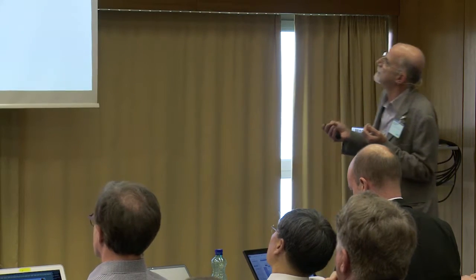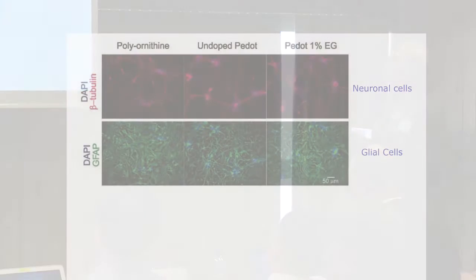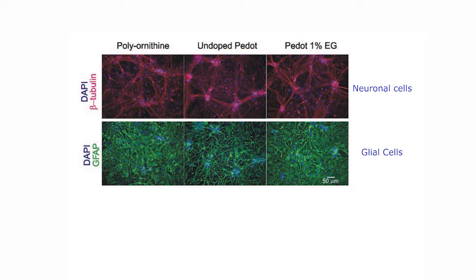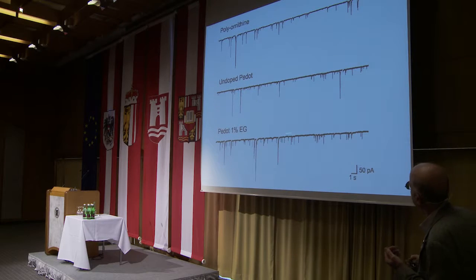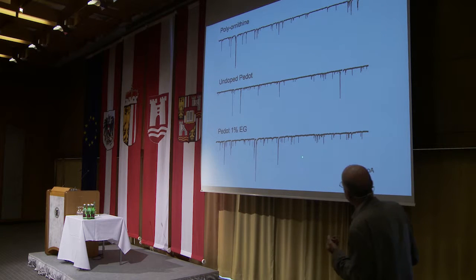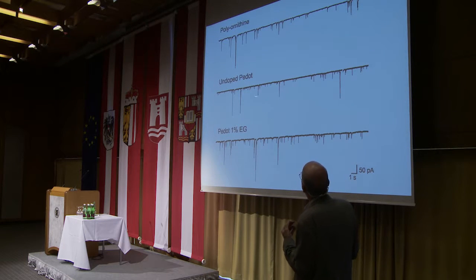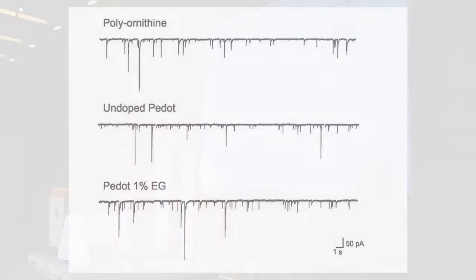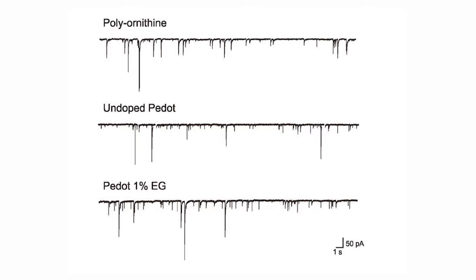And we can see that, in fact, neurons grow very well. Also, glial cells grow very well on this material. However, the spontaneous activity of the neurons on this substrate is very similar to polyornithine, which is a standard substrate used for these cultures.